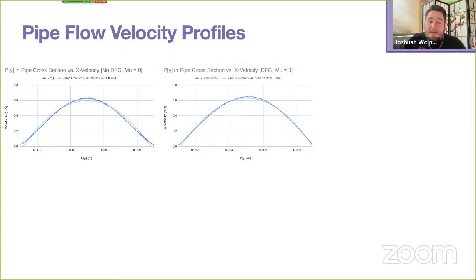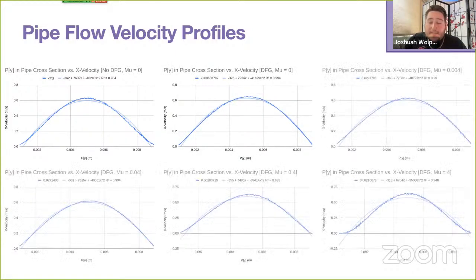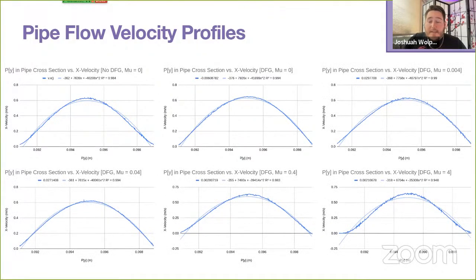And conversely, when we add solid fluid coupling, we get a great quadratic fit. And similarly, when we add fluid viscosity, we again get pretty good quadratic fits. However, for higher viscosities like the last two runs with 0.4 and 4, we actually see something closer to a trapezoidal distribution, seeming to indicate that we measured these two while they were still in their entrance regions. And this is actually expected since a more viscous fluid will naturally have a longer entrance region.